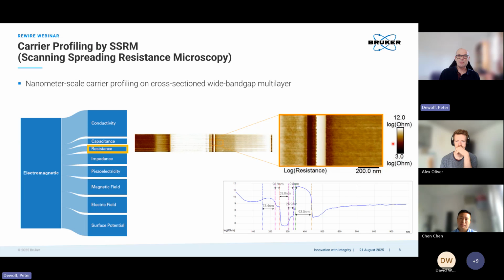You can see if we make a cross section through this - because these are always nice color images, but what is really of interest are the values - the resistance varies from, on this logarithmic scale, below 6 to well above 11. So we have 5-6 orders of magnitude of resistance change, corresponding to carrier concentration changes typically from 1E15 to 1E21.